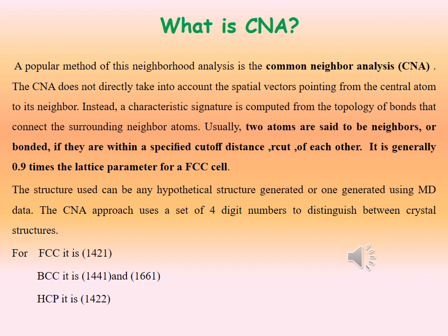Now coming to CNA. CNA stands for Common Neighbor Analysis. CNA doesn't use any spatial vector pointing from the central atom to its neighbors, rather it characterizes a neighborhood of the central atom. Two atoms are said to be nearest neighbors or bonded if they are within a specific cutoff distance, that is known as the R cut. For a FCC cell, it is generally 0.9 times that of the lattice parameter.